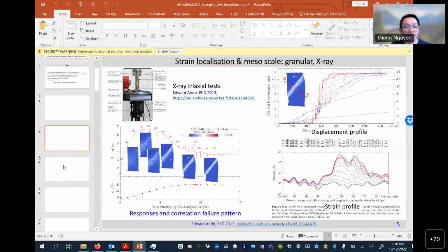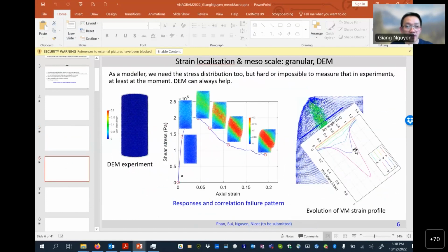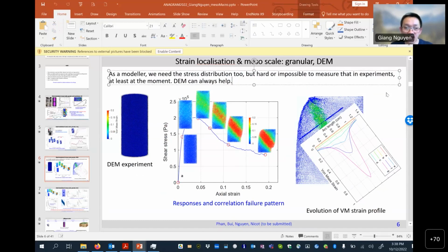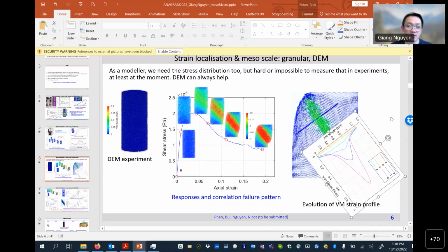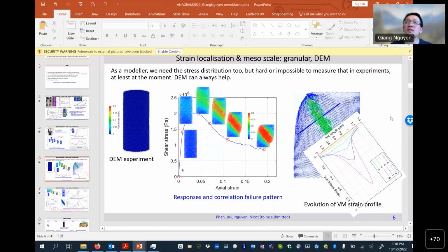Yes, so say here, if you run a DEM experiment or any experiment that allows you to plot the evolution of strength across the band, as you can see here, then you can use the kind of fitting in a loose sense. I think they use the Gaussian distribution with a length parameter. So if you manage to fit this profile with some parameters of the Gaussian or some form of distribution that has a length scale, the perfect fit will give you an indication of a length associated with the fit. So if you do that for different profiles, you get the evolution of the band thickness.